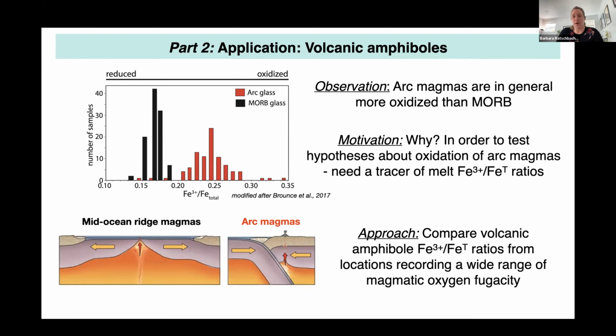But in order to test some of the hypotheses which are out there, we really need a good tracer of melt ferric over total iron ratio or of melt oxidation state. And the idea we had was thinking about amphibole, because it's such a common mineral in subduction zone magmas, to develop as such a potential tracer. And the approach we took with the study is to compare volcanic amphibole ferric over total iron ratios, which we can measure using synchrotron Mossbauer spectroscopy, from localities which record a relatively wide range of magmatic oxygen fugacities. And then we can see whether there is a correlation of the ferric over total iron ratio in the amphibole we can analyze and the redox state of the magma from which they crystallized.